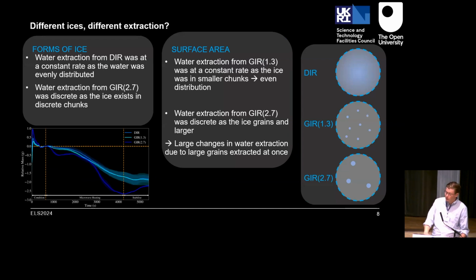So for what I was looking into, I tried to come up with some preliminary thoughts on why these things were occurring. For the forms of ice, the water extraction from the diffuse ice is at a fairly constant rate. That's probably just due to the fact that the water is diffuse across the sample. So as the sample heats up, the water is released at a fairly constant rate. And this is probably also the reason why it happens with the smaller grain sizes.